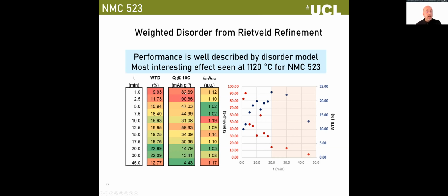Again, the relevance of the colors is that high capacity is red. In this case, low weighted disorder is more red, because the suggestion is that low weighted disorder is somehow better. Well, it turns out it's not. And then on this column, we're again plotting that ratio of those XRD peaks, the 003 to 104 intensity ratios, and anything near 1.2, which is what people think is good, is what we've plotted here. So the truth is none of this really makes any sense.